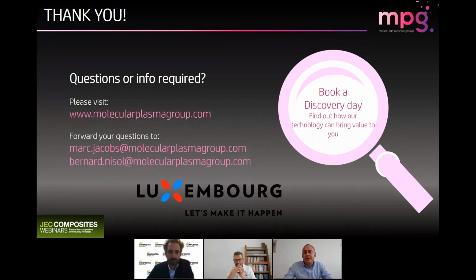To address the question of Katalin Fotea, I'm personally surprised to hear numbers such as 6 months and 2 years for PP activation with Corona. I'm not saying it's impossible, but I think that if you want that with Corona, you have to treat your surface like crazy so as to have a very high cross-linking degree of the surface to avoid the hydrophobic recovery.